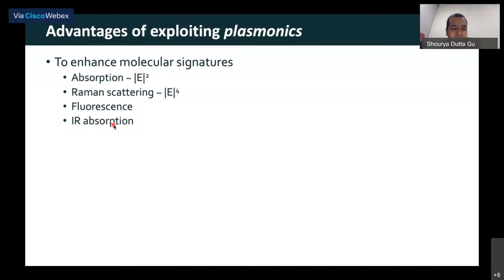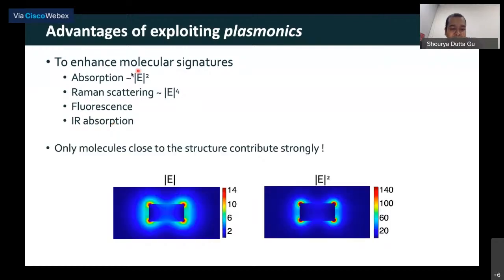Now if I just look at these simple variations, let's say this is the electric field modulus. If I put my molecule far away from the structure, it will not absorb a lot of light because the electric field is low. However, if I take that same molecule and put it near these corners where we have the high electric field, the absorption will be enhanced by the electric field modulus squared, as shown here. So if I put the molecule at this corner, the absorption of that same molecule will be enhanced by a factor of 140.